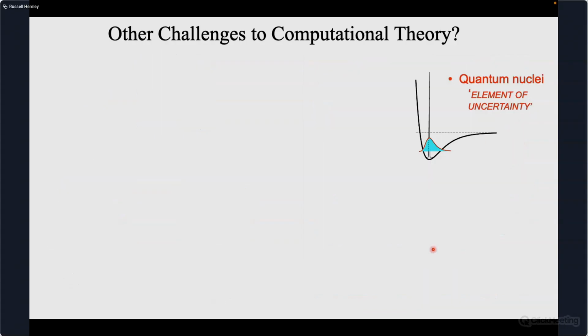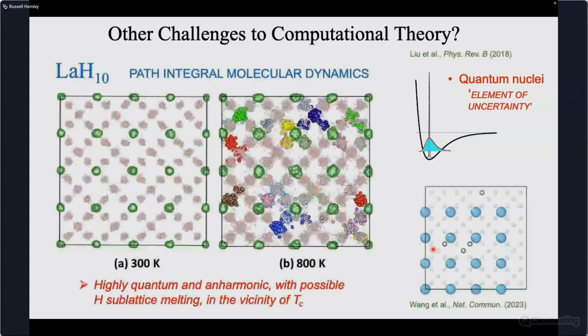Another challenge to theory is actually looking more fundamentally at what's happening in these systems, because I mentioned these systems are highly quantum systems. Hydrogen is a quantum element, and there's kind of a quandary here in the fact that when we do calculations of the dynamics, what we find is something quite curious. Because of the highly quantum character and anharmonicity in these systems, the materials are highly diffusive with respect to the hydrogens, but we're using a harmonic approximation typically when we do the calculations of the TC. In fact, near TC for some of these systems, you have sublattice melting or partial melting. So it's very, very anharmonic, almost diffusive.